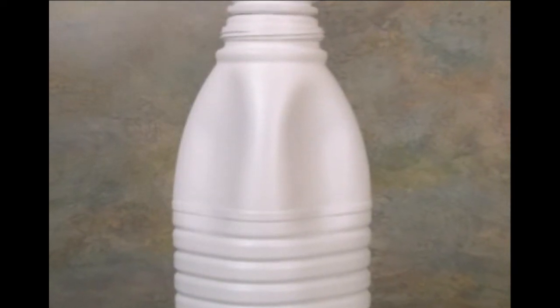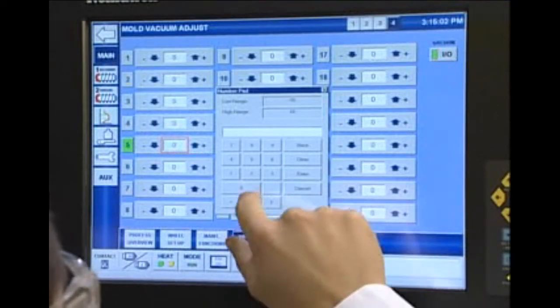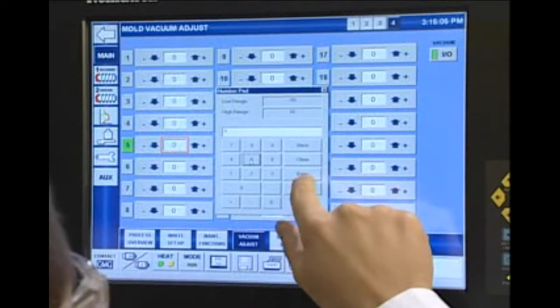During the molding process and before bottles are sealed, a controlled amount of air is pulled out of the bottle to prevent retained heat from swelling the bottles after discharge. As needed, fine-tuning vacuum adjustments are made from the PC control system.